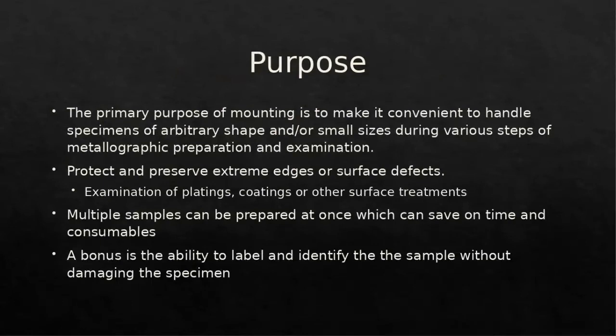of why we mount samples, the biggest one is making it convenient for you to handle the specimens. Not every sample is going to be easy to work with, so it really helps because you might have an irregular shaped or just an awkward geometry, fragile samples, maybe even super small in size that you cannot just hold with your bare fingers. So it makes it very convenient to be able to proceed through these metallographic steps without taking your fingers off.